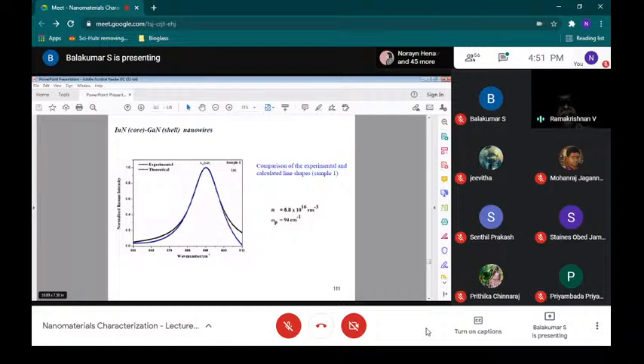Because you evaluate the carrier concentration, that also you try to fit with your experimental data. So when you have the experimental line shape and the theoretical line shape, this theoretical line shape matches for the condition when the carrier concentration is 8.8×10^16 per cm cubed, and the omega frequency is 94 wave number. Or you just put it as n, and later you deduce omega p. So for each n value, once you know the column size or the wave number, you try to find out omega p and n. So you can theoretically predict the column size, and theoretically predict the carrier concentration. Next slide.